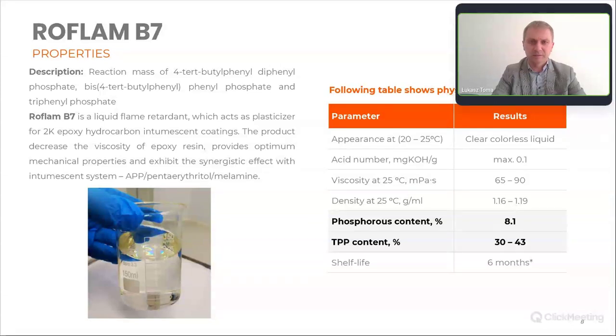So what about other properties? Basically, this product is in the form of a clear, colorless liquid. The viscosity is relatively low, in the range of 65 up to 90 millipascal seconds. But what is important, the phosphorus content, which is necessary to provide appropriate fire retardant properties, is 8.1. And the product also contains a significant amount of triphenyl phosphate, TPP. The content is in the range of 30 up to 43%.